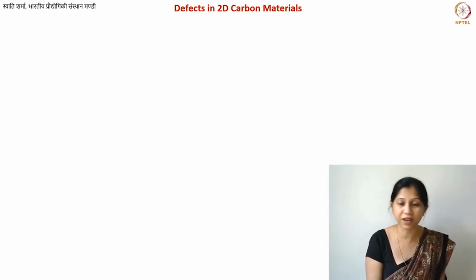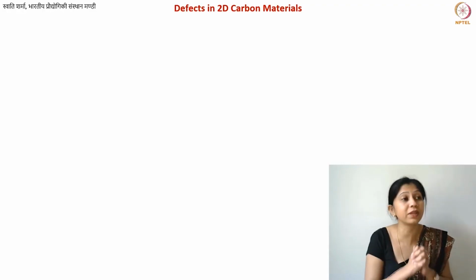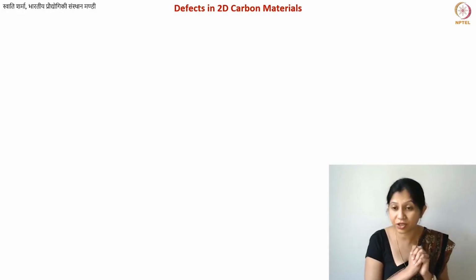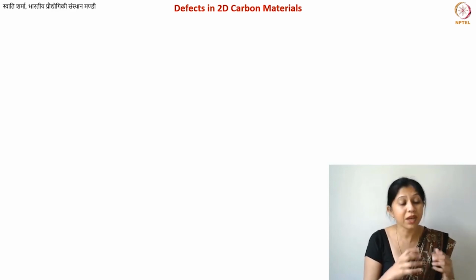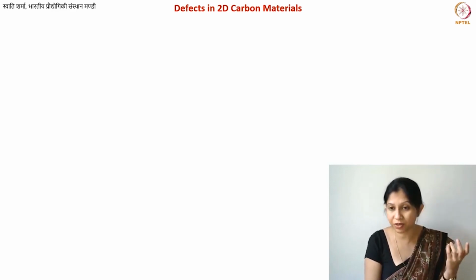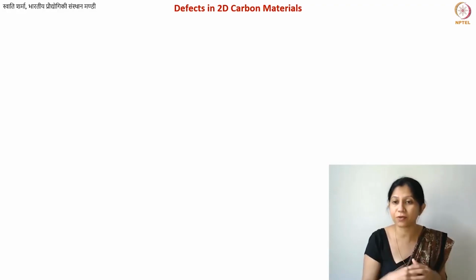Okay. Also, in the case of graphitizing carbons, it's not like graphitizing carbons do not have any defects. Otherwise, we wouldn't have to anneal them out. So we perform the graphitization at very high temperatures. We perform the annealing because we want to get rid of these non-six-membered rings. And that is how we actually increase the diameter of our crystallite. So we increase the La.